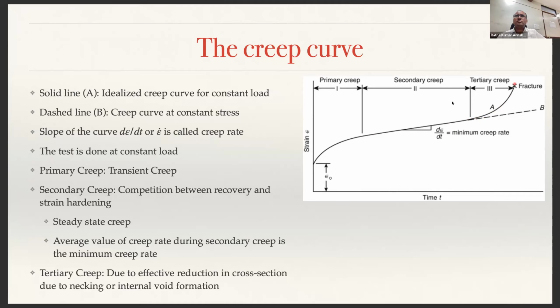Okay. So this solid line that you have seen here is what we call the idealized creep curve for constant load, and dashed line B is for constant stress. Why are these two deviating? Because when the fracture is happening, the cross-sectional area will be changing, and hence the load per unit area will change. This is only load, and this is for constant stress. So that is why this line B is representing constant stress, wherein the cross-sectional area is reducing.